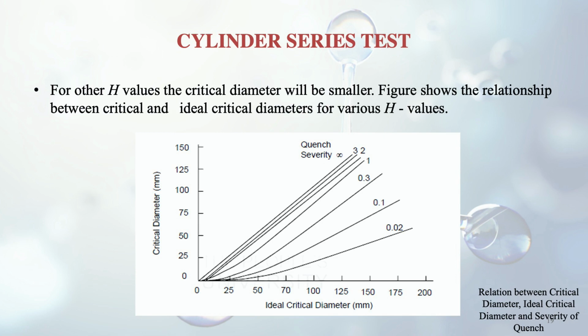So quench severity is given there, and different H values are being given with different graphs. Like you see at the bottom there is 0.02, and if you go to the top, then there is infinity, and at the infinity H you can see that both critical diameter and the ideal critical diameter are the same, meaning the slope is 45 degrees. So you see from the graph on that line of H equal to infinity, if the ideal critical diameter is matched on the critical diameter axis, then both are the same. For example, you go with 50, so 50 on the ideal critical diameter will be the same 50 on the critical diameter axis when H is equal to infinity. And when we move down, then the ideal critical diameter will obviously be larger than the critical diameter.